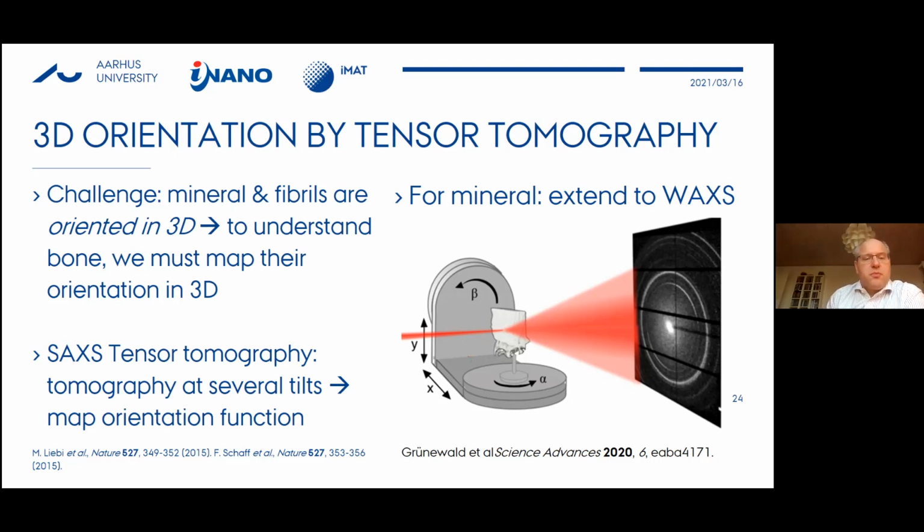This turns out to be rather difficult, but it turns out that you can use the fact that small angle X-ray scattering is anisotropic. So this is the signal very close to the beam stop on the image on the right. I will just quickly point it out. So this would be the small angle scattering signal right here. And you can see it's not circular in shape. This curve reflects the orientation of the collagen fibrils more or less.